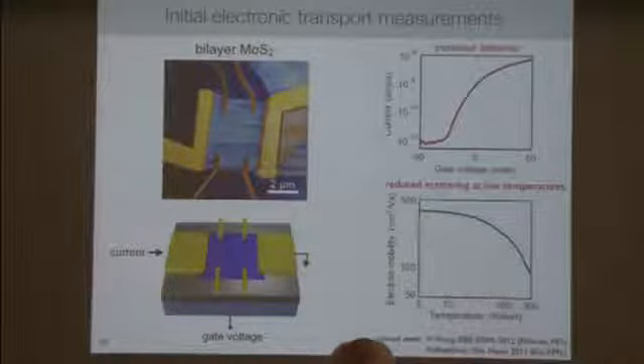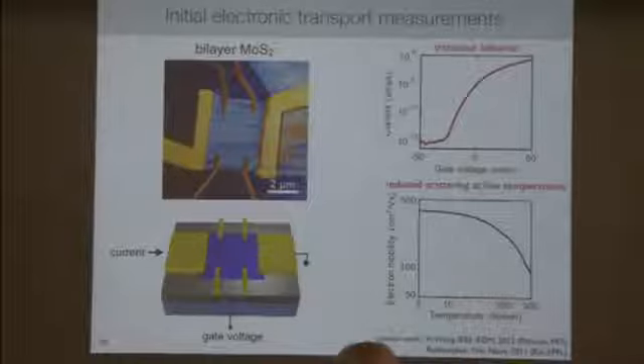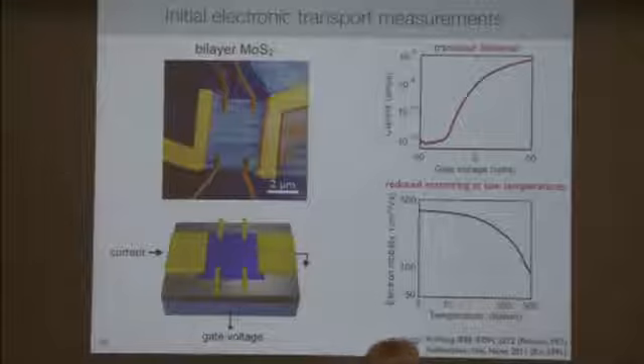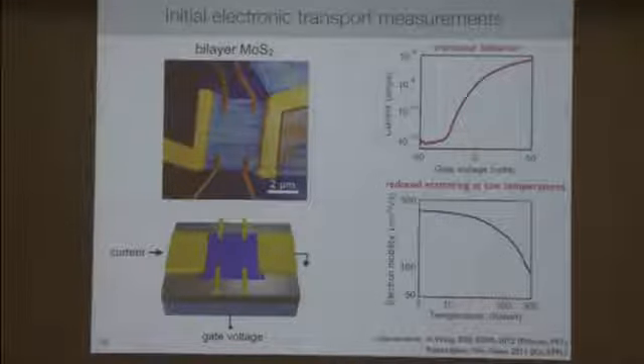In addition, when we want to investigate the intrinsic physical properties of these materials, we'd like for the electrons to travel a long way through the material before they hit some impurity and change their direction. And this length that they can travel before that happens is quantified by the mobility, which we found in these devices to increase substantially as the temperature was reduced. So I should say that while these values are state-of-the-art for these materials, they're not as high as we'd like, and so improving this number will be a focus of future work for these materials.